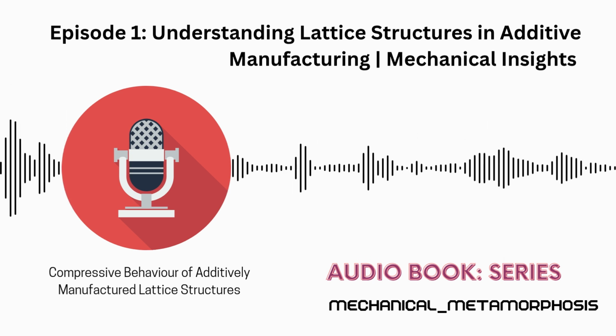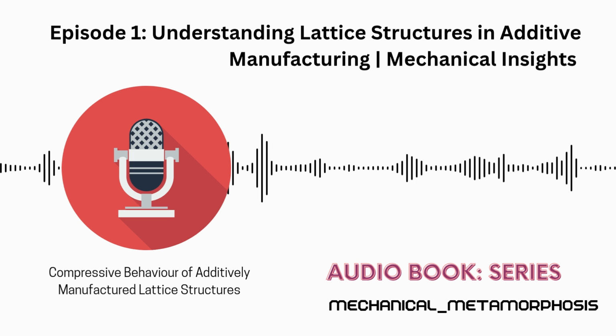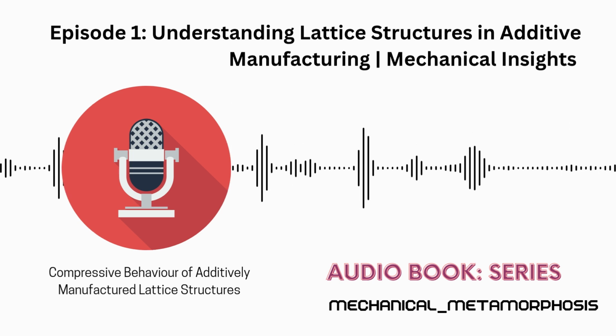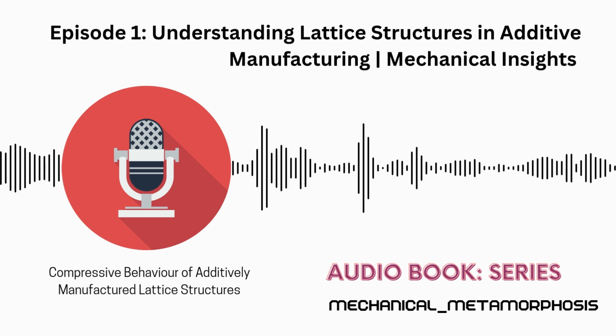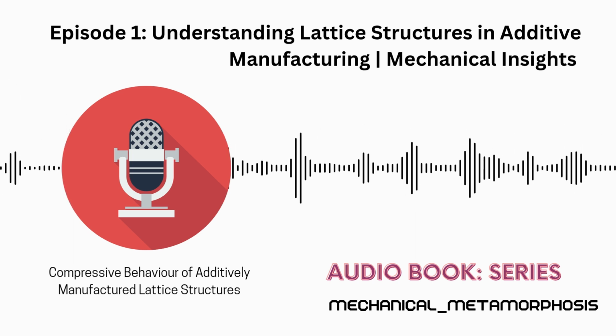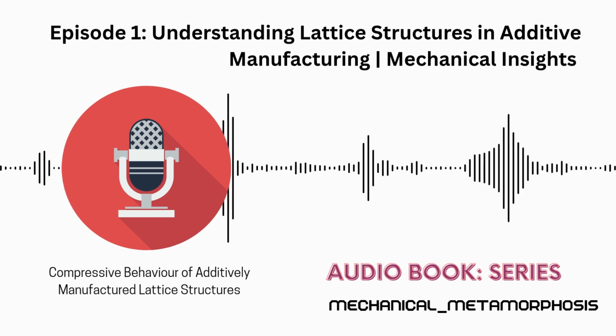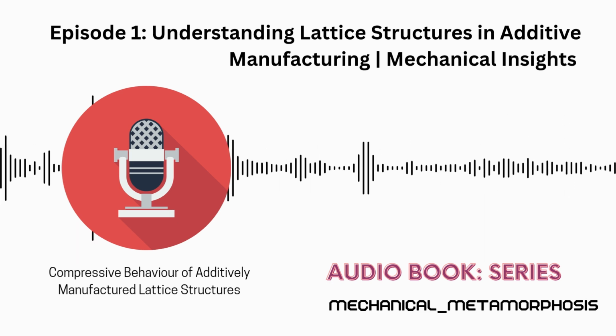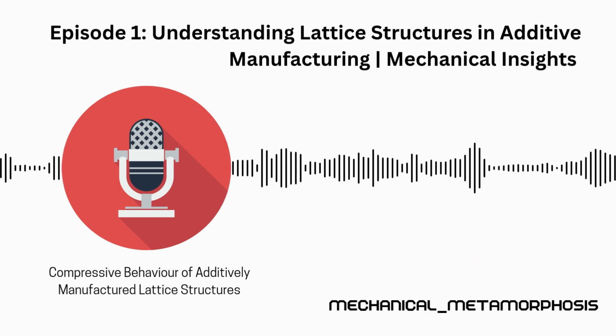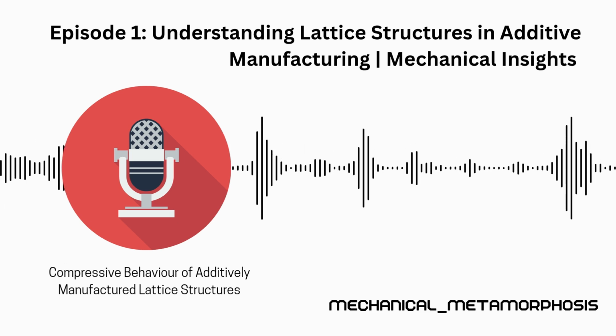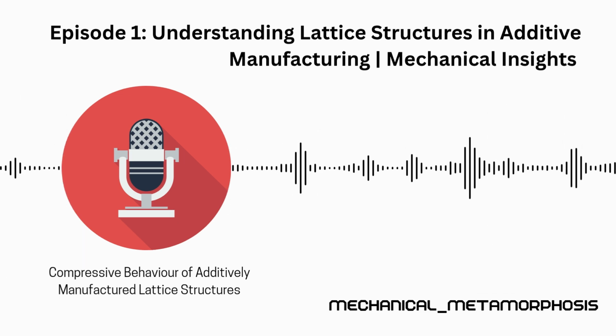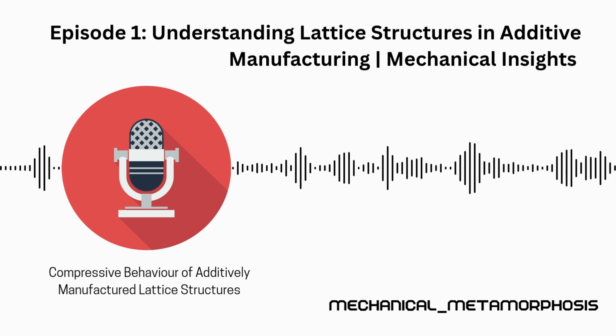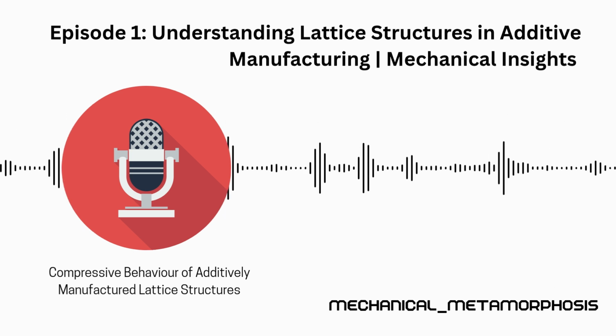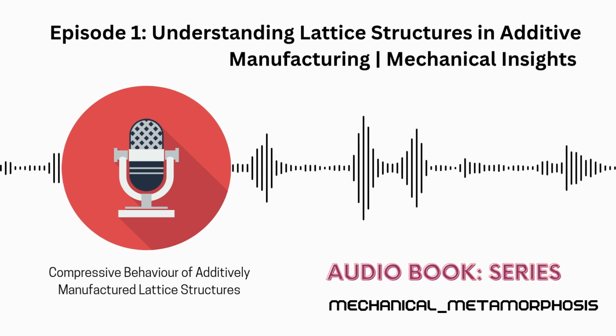Okay, makes sense. What about weak points, like the joints, the nodes? Yes. Stress concentration at the nodes is a classic failure point. Bai et al. tackled this with the graded strut BCC, GBCC. Graded strut. Yeah, they increased the radii, the roundness of the corners where struts meet the nodes. And that helped. Big time. It shifted the failure point away from the nodes. Standard BCC tends to fail right at the node. This is a major step for integrity.